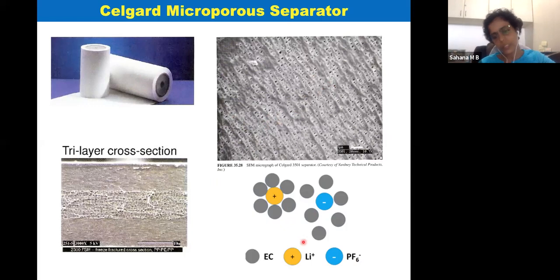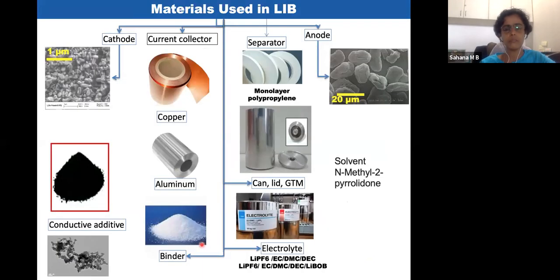And now about the liquid electrolyte, this is a salt, which is this yellow colored lithium, and PF6, another anion. Now this is a salt, which is a solid that is dissolved in some organic liquid electrolytes, for example, the EC. So only the lithium goes into the anode and the cathode. Now, what are the materials? Is it only these materials that go into a lithium ion cell? No, there are many other materials also.